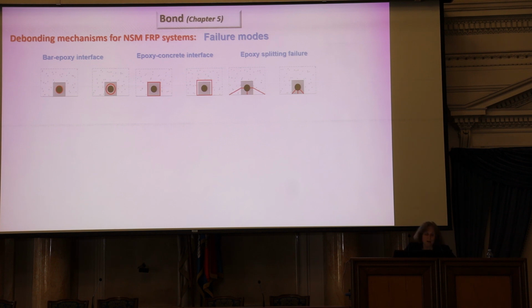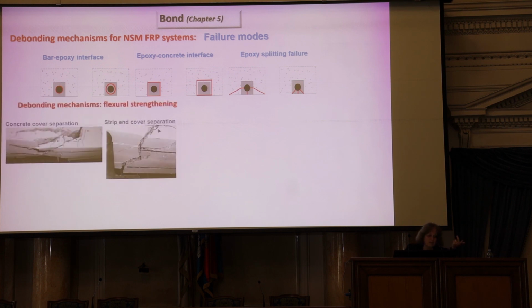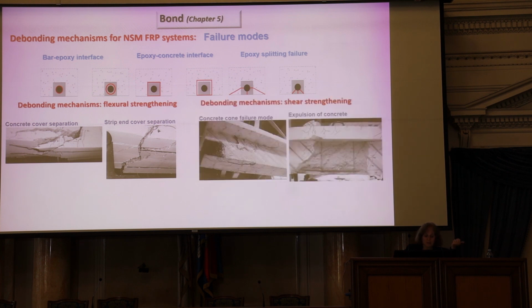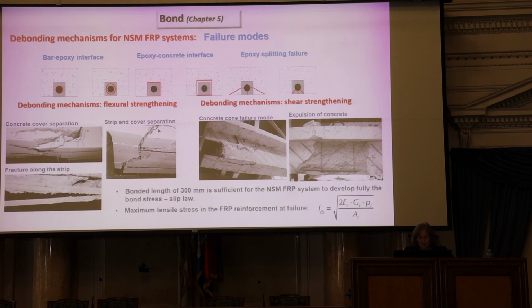Debonding mechanisms for FRP near surface mounted FRP systems. What I showed you here in the previous slides was externally applied laminates. In near surface mounted systems, the resilience is greater. You can have a number of possible failure modes. For instance, you can have failure at the bar epoxy interface. You can have failure at the epoxy concrete interface. You can also have splitting failure that crosses the epoxy and splits the adjacent cover. So all sorts of such things may happen.